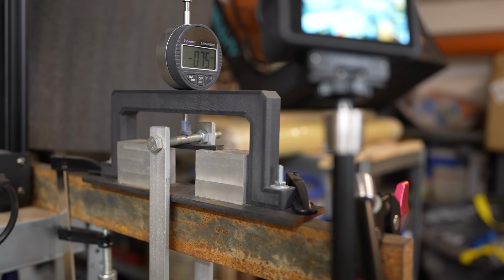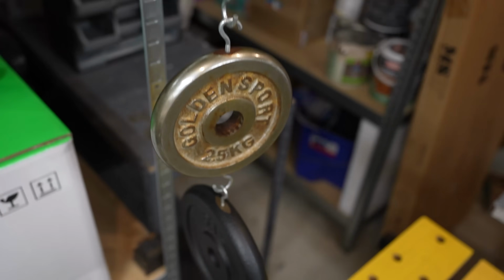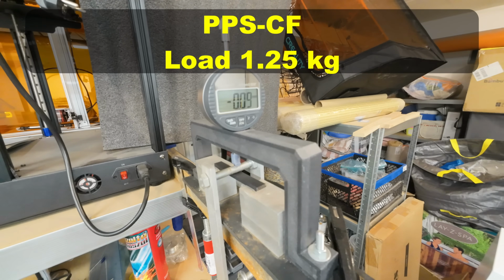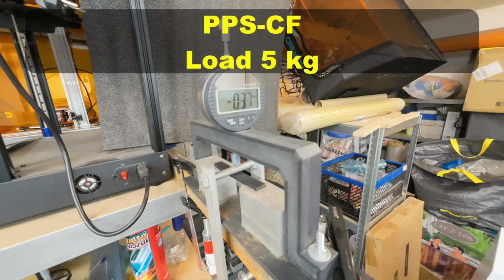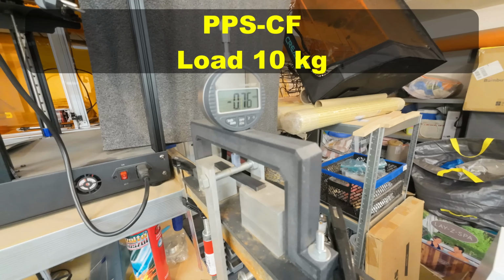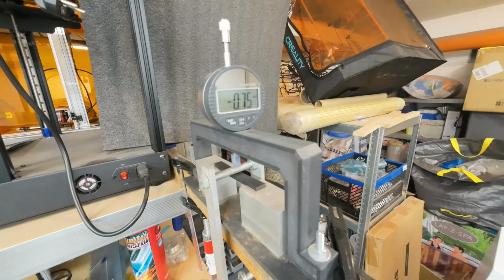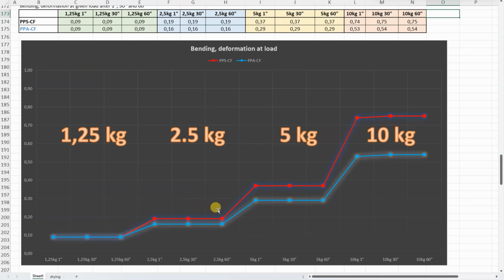3-point bending test, distance between supports is 50 mm, and I'm placing these loads one by one and measuring the deformation after 1, 30 and 60 seconds. The load is 2.5 kilograms. This is the deformation under 5 kilograms and under 10 kilograms. With the load removed, almost zero deformation. In this test, yes, it has more deformation compared to the PPA-CF, but even then this is a very strong and stiff material, and look at this, no additional deformation over time, even under 10 kilograms.